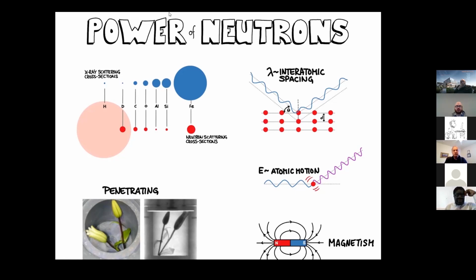The fact that neutrons have a small cross-section for lead, but it's large for X-rays, is illustrated in the photograph below, which shows a neutron radiograph on the right-hand side of Asiatic lilies in a lead cask. So the neutrons just blow right through the lead, and they scatter, and you can see the contrast with the Asiatic lilies, primarily the hydrogen within them.